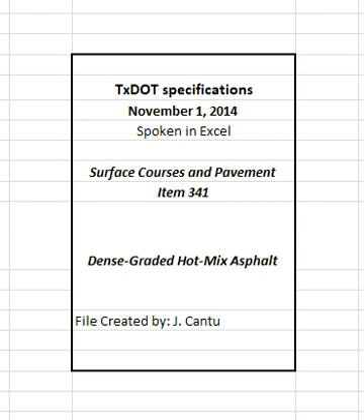4.9.2.3 Production testing. The contractor and engineer must perform production tests in accordance with Table 14. The contractor has the option to verify the engineer's test results on split samples provided by the engineer. Determine compliance with operational tolerances listed in Table 11 for all sublots. Take immediate corrective action if the engineer's laboratory-molded density on any sublot is less than 95% or greater than 98% to bring the mixture within these tolerances. The engineer may suspend operations if the contractor's corrective actions do not produce acceptable results. The engineer will allow production to resume when the proposed corrective action is likely to yield acceptable results.